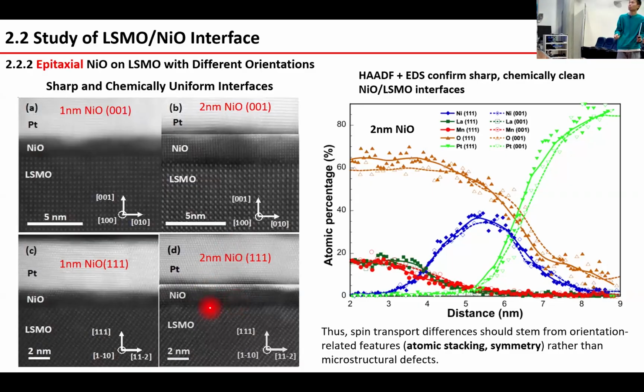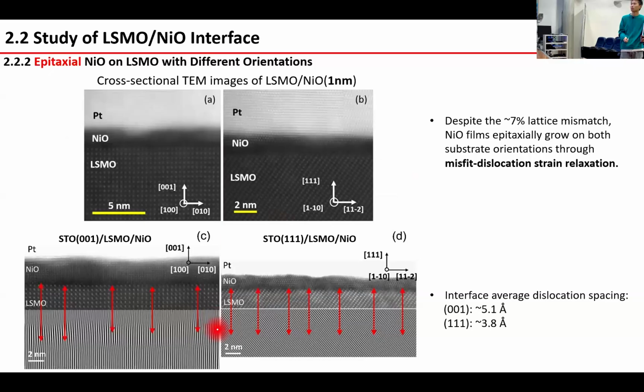Regarding the dark interface, I think it's also due to changing the contrast. And also, as I said before, there's a 7.7% lattice mismatch between the nickel oxide and LSMO, so it might have some dislocation. We also measured the dislocation spacing of the nickel oxide and LSMO interface. Yes, I understand this. I just don't understand the TEM images. I have trouble seeing where a layer ends and another begins, and why we have some white or black lines.